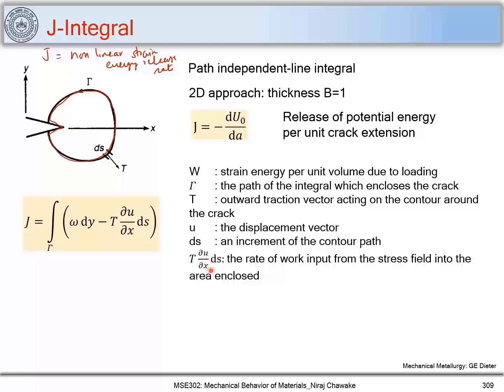T del U upon del X into ds gives us the rate of work input from the stress field into the area enclosed. So when this crack extends, there will be a release of the strain energy, and there will be a work done to form a new surface, or there will be an increase in the energy to form new surfaces, or that can be accounted for by considering this rate of work input from the stress field into the area enclosed. So what is the energy required or work input which is caused when the crack extends?